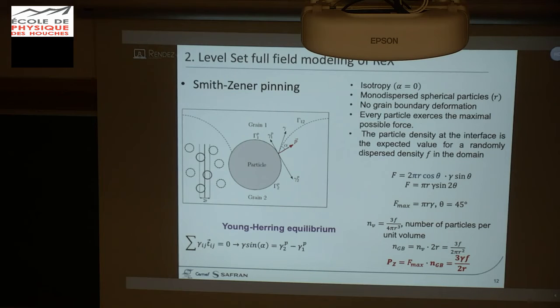And of course, this limiting grain size is used industrially to limit grain growth during thermal treatments of nickel-based superalloys. But with level set full field simulation, you can directly respect the interaction angle between the grain interface and the second phase particle, without introducing in the kinetic equation an approximation of the Smith-Zener pinning pressure. Finally, in the full field simulation, you can respect the angle of interaction and the modification of the local curvature, and the Smith-Zener pinning pressure will be naturally taken into account in the simulation.